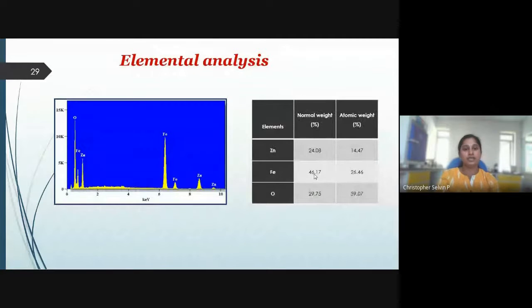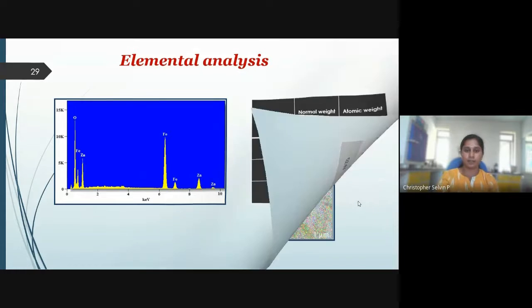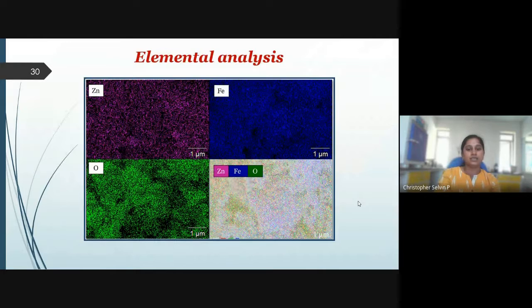And followed by that, we made elemental analysis. Only desirable elements exist in the sample matrix, like zinc ferrites. Zinc, Fe, and O composition was estimated by means of EDAX analysis. The atomic weight percentages indicate relatable values for all the elements, which fall in the line of the certain ZnFe2O4 composition. The even distribution of these elements across the sample is illustrated by means of EDAX mapping.